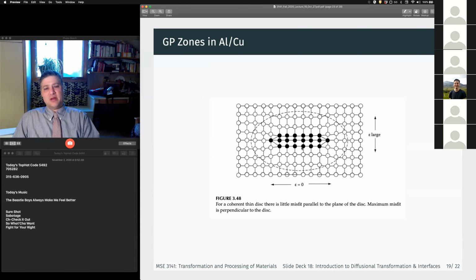So instead, we go through a series of intermediate phases, and the first that forms is the GP zones, which are just clusters of copper atoms, right? And copper and aluminum both form FCC, so the local structure in the GP zone is still FCC. But we have an anisotropy in terms of the interfacial energy and with respect to the elastic modulus. So we get a cluster where they form these plate-like or disc-like structures with a high degree of elastic misfit in one direction, perpendicular to the plane of the surface, and a much smaller interfacial energy, much smaller elastic distortion this way, right?